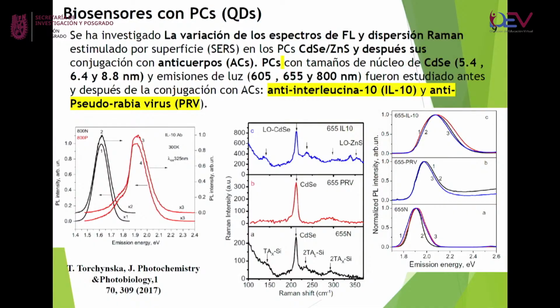You could see here, for example, the quantum dots without bioconjugation. Then you could see here conjugation of quantum dots to pseudo-rabies virus. You could see that the band shifts to the higher energy side, and you could see here the luminescence with bioconjugation to interleukin antibody. This shift is more significant.